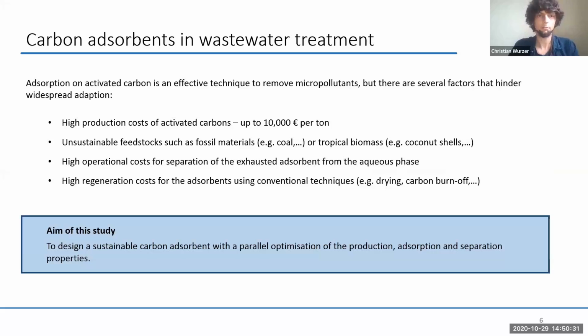However, the obstacles of high production costs of up to 10,000 euro per ton are quite an obstacle. Furthermore, activated carbon is usually produced from unsustainable feedstocks such as coal as a fossil material, or in some cases from tropical biomass such as coconut shells. Additionally, you have high operational costs for the separation of the exhausted adsorbent from the filter. Just imagine a wet carbon powder that you have to remove from a water phase. So that's usually done by centrifugation or another filtration step, so quite expensive too.